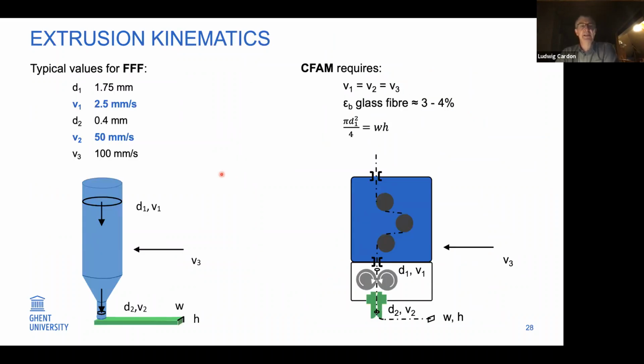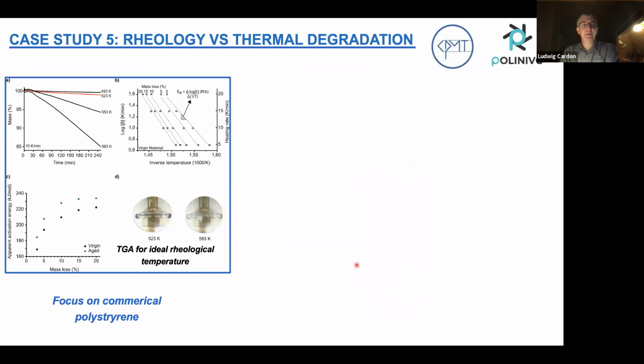And we also investigate the flow of the material, because a normal 3D printing filament has a certain flow and they spread out a certain section. So in our system, the fibers will pass through the infiltration system, but then we have to pay attention to the speed of deposition compared with the filaments, the fibers which are passing by here. So the fibers, when they are glass or carbon fibers, they are, let's say, not flexible, which you have in a standard 3D printing of your polymer. You have the viscoelastic behavior. So in the scope of the fibers, we must pay attention that the speed inside this one is completely equal to the deposition rate you apply. So that's also what we try to investigate.